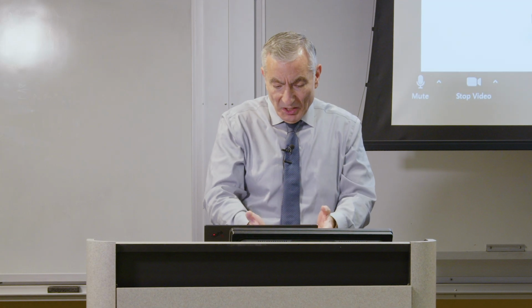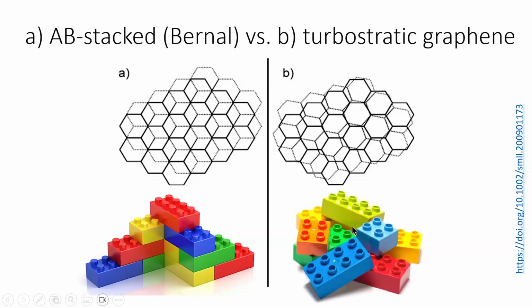It's like, in a way, pulling apart Lego blocks. Sometimes you've got to kind of work at that. But if the Lego blocks are just thrown on top of each other, it's very easy to get these apart. This is turbostratic graphene, remember, where you had no particular ordering. It's different than if you take graphite and you try to separate graphite into individual layers. There you have to invest a lot of energy to pull this apart. Here you don't have a good electrostatic interaction between the sheets.